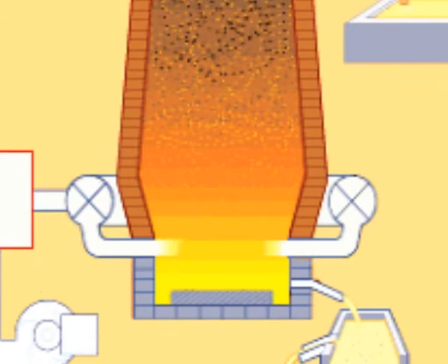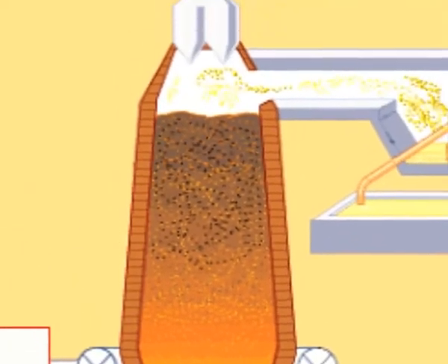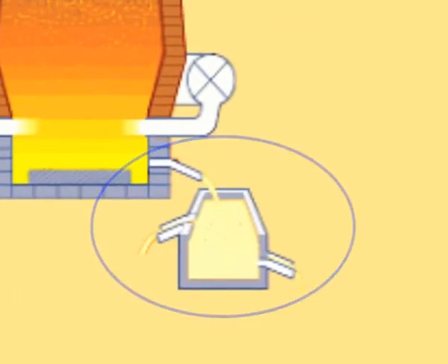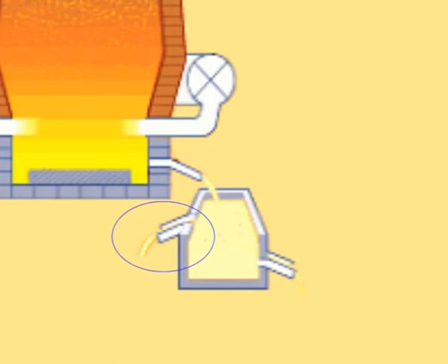This procedure is similar to that followed in an iron blast furnace, with the important difference that the major products of reduction here are a zinc-bearing gas and liquid phases that separate in the furnace hearth and are tapped periodically. The liquids consist of molten lead containing recoverable copper and silver, and the gangue content of the charge in the form of a molten oxide slag.